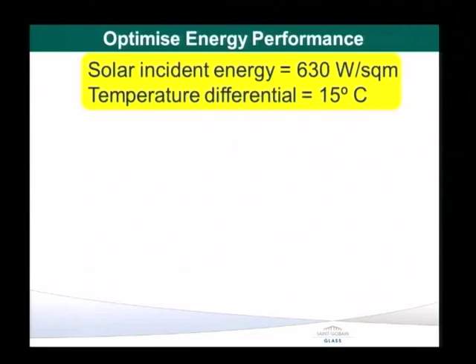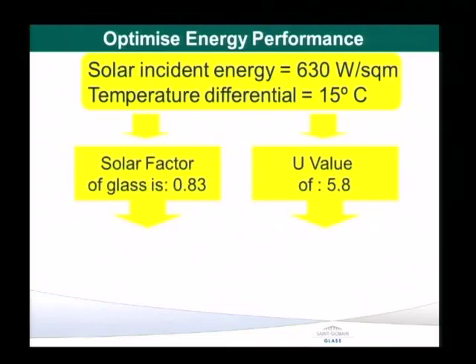Let's see how this affects a building. Consider an average summer day where it's 38 degrees outside and 23 degrees inside, a temperature differential of 15 degrees. The solar incident energy at around noon is about 630 watts per square meter. This can go much higher. Let's consider a clear glass with a solar factor of 0.83 and a U value of 5.8.